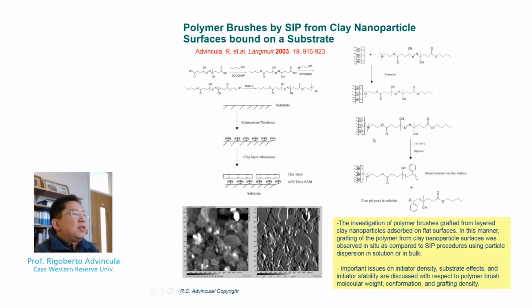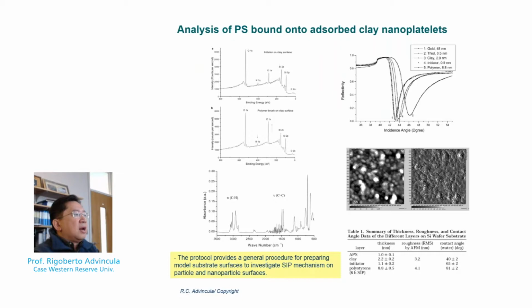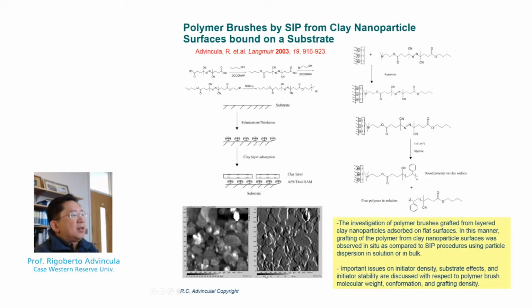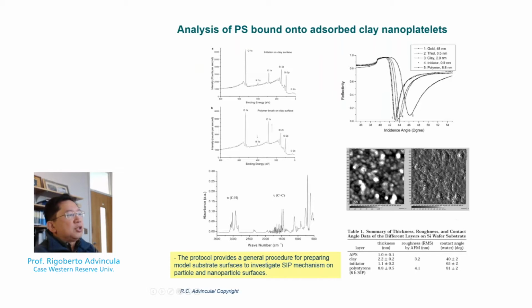Here is a polymer brush grafting where we actually observe the nanoclay surface by atomic force microscopy after the polymer has been grafted directly on the nanoclay. So this was verified by this AFM image, as well as the XPS, and a technique called surface plasmon resonance spectroscopy that shows the change in morphology after the grafting of the polymer on the surface. So to switch back, this is the nanoclay platelets before polymerization, and after polymerization, you can see the change in morphology. So atomic force microscopy here is a critical technique for characterizing the morphology change on the nanoclay surface.